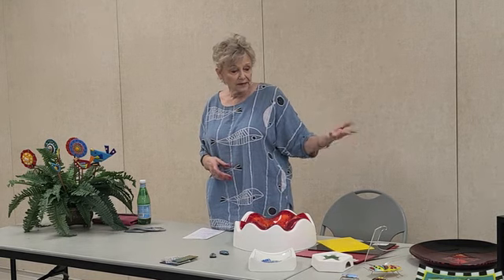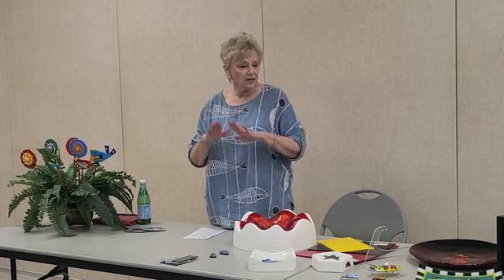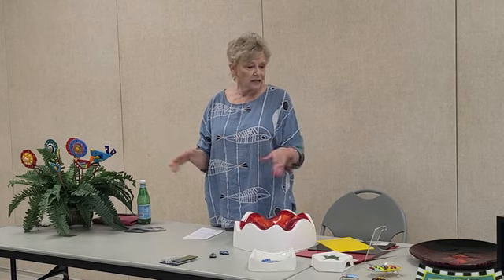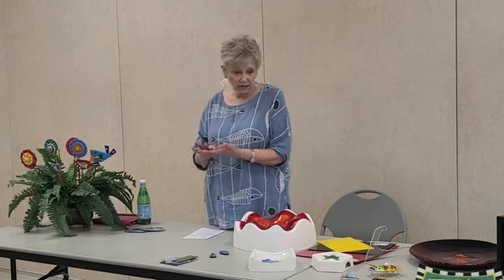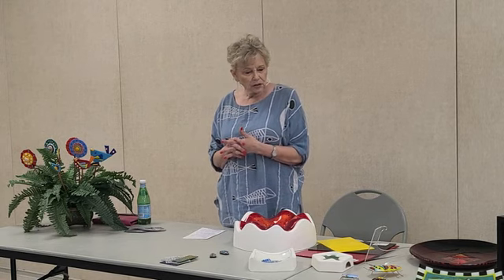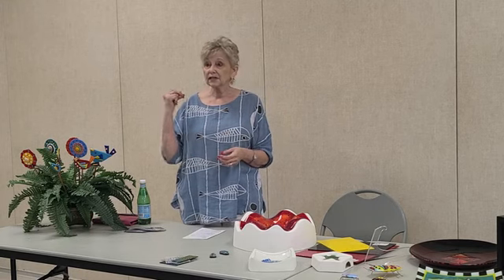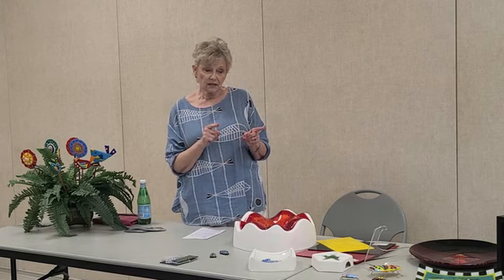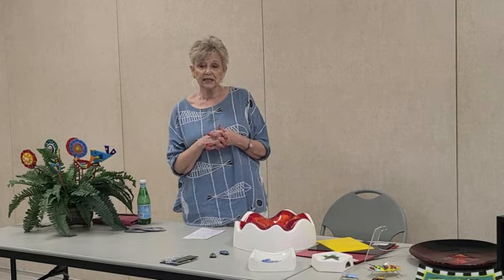So I probably then turned it up as fast as I could, in my kiln, to about 1475, so that it got that smooth finish, nice and glossy, flat, nothing bumpy; you can't feel a difference in the stripes or the lines. And let it sit at 1475 for probably 10 or 15 minutes. Then you have to drop the temperature as fast as you can, because there's a range of temperature in some of the glasses that will cause something called devitrification.